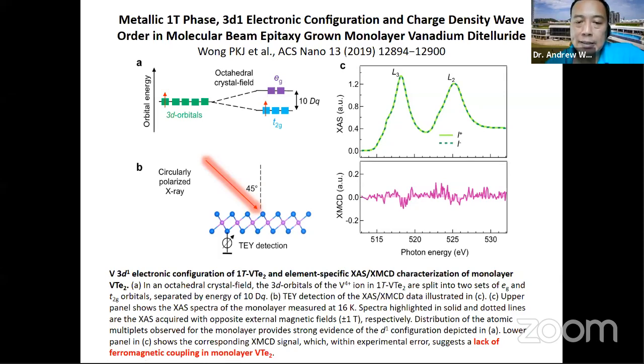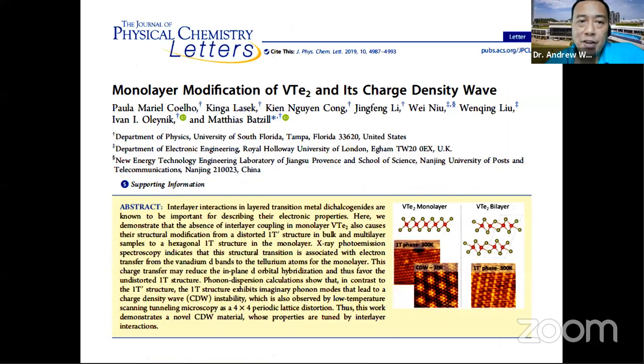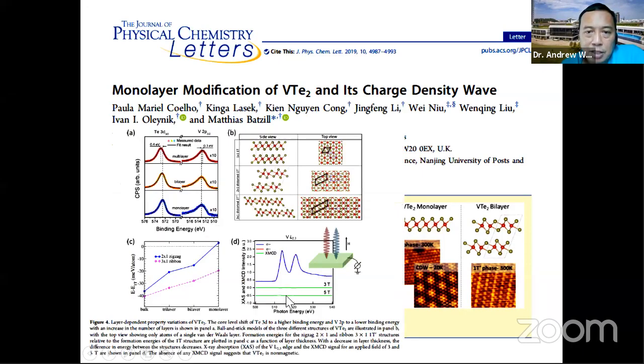vanadium dichalcogenide compounds are not intrinsically magnetic. And in fact, our work is supported by the Batzill group, the same group that showed that vanadium diselenide was magnetic at room temperature. They also did vanadium ditelluride, and in this case, they didn't observe magnetism. So the XMCD signal, you can see there's no dichroism. So in fact, we think then that the first conclusion may not have been correct.